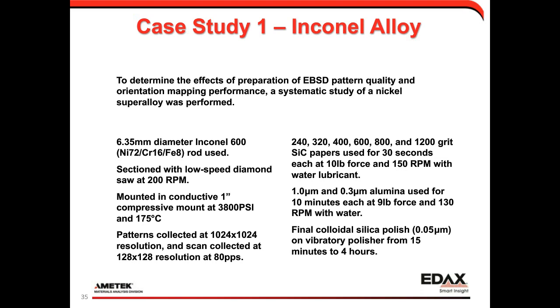And to give an idea, I started with 240 grit silicon carbide paper, stepped through from 240, 320, 400, 600, 800, and 1200 grit papers, used each paper for 30 seconds, used 10 pounds force and 150 RPMs using water. After those grinding steps, I switched to using the imperial cloth, using 1 micron and 0.3 micron alumina for 10 minutes each at 9 pounds force, so a little bit less pressure, and 130 RPM, a little bit less speed, and using a water drip. I didn't want to completely flush away the abrasive, but I'm trying to keep it a little bit clean. And then I go to colloidal silica, again on an imperial cloth and a vibratory polisher, starting at 15 minutes, going to 4 hours. And what I want to do now is sort of present those results.